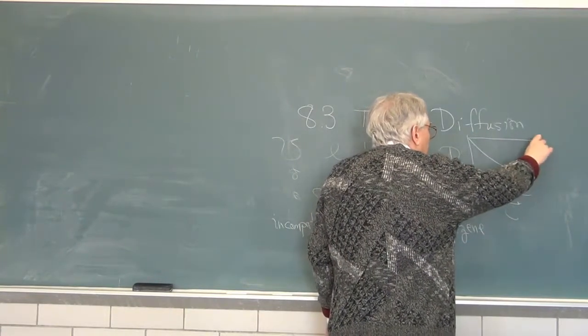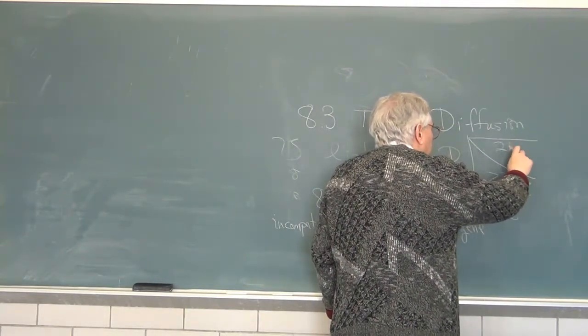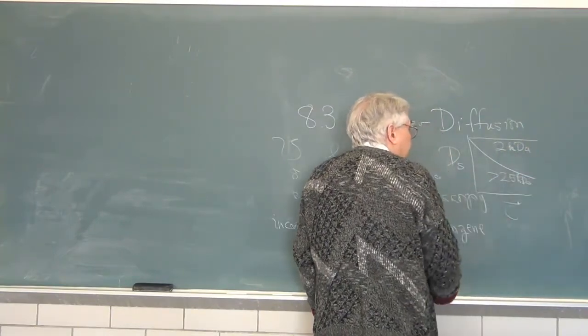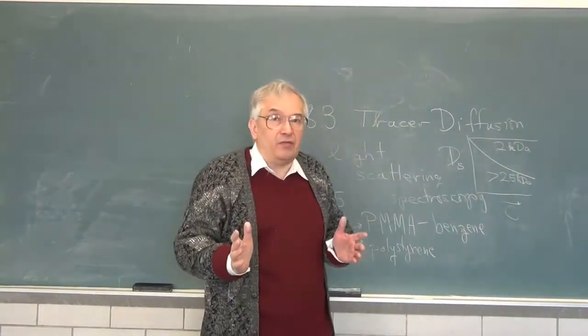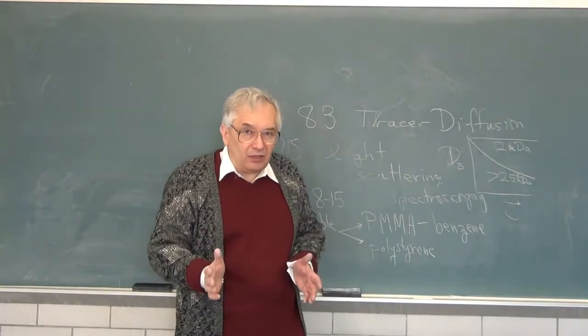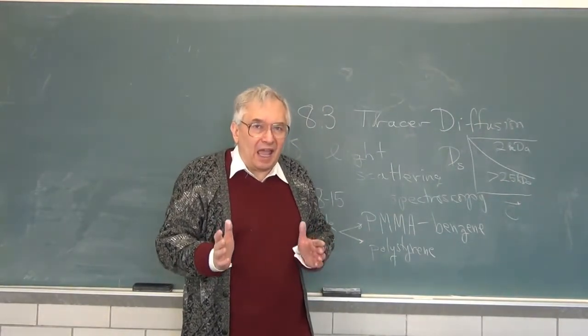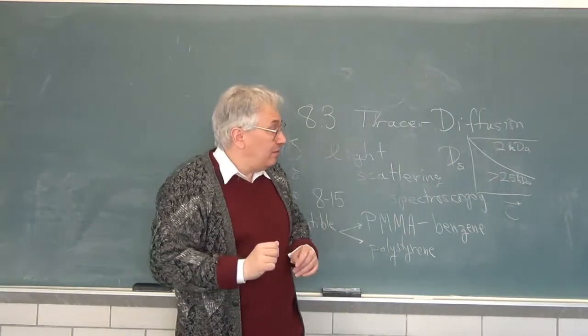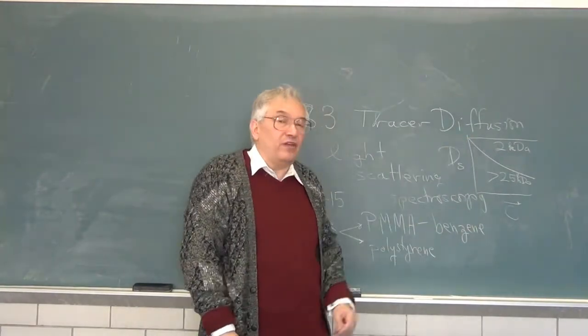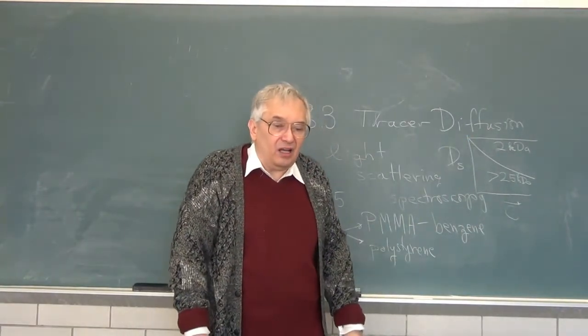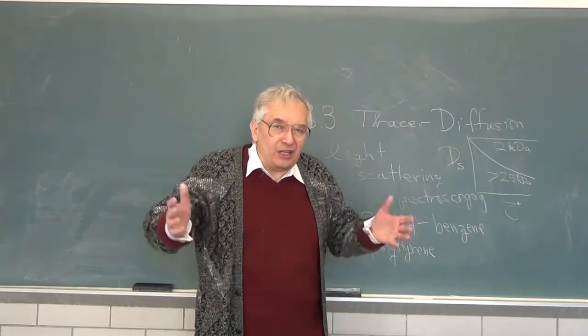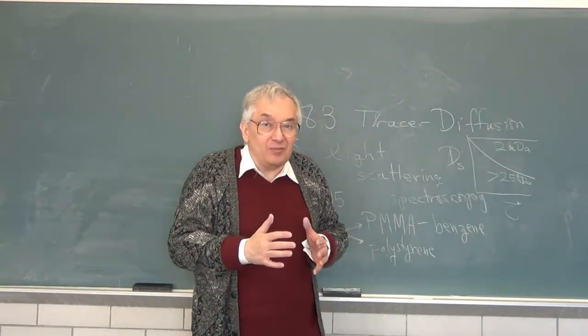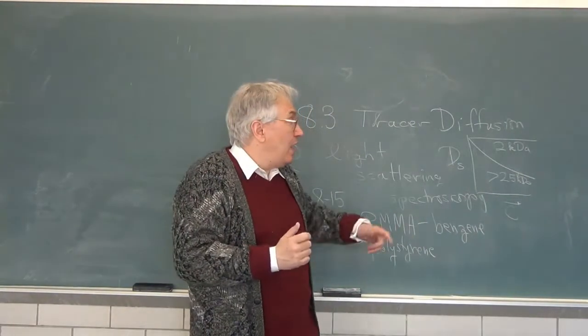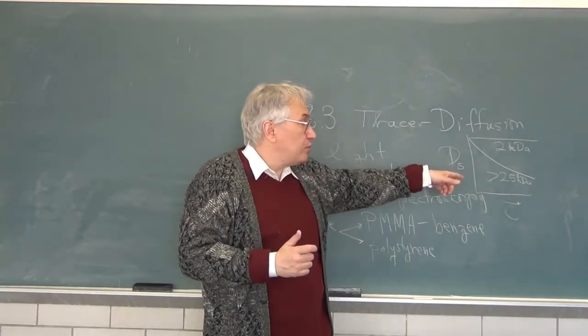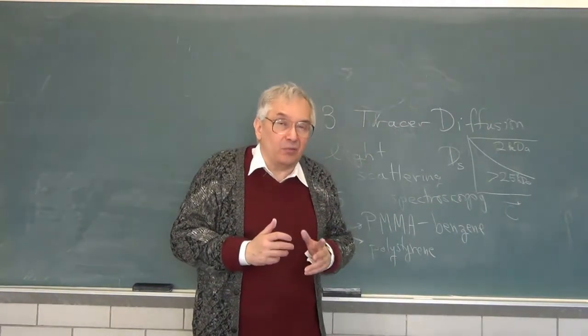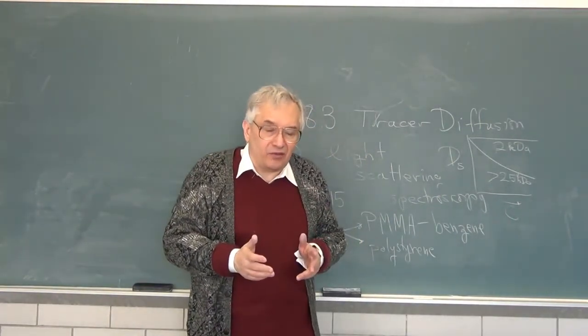But if we're down at a polymer of about 2 kilodaltons, which is a very low molecular weight, what happens is that the diffusion coefficient just sits there. The polystyrene chains don't shrink up on themselves because it's a very short chain. And also, they apparently aren't retarded very effectively in their motions by the presence of the matrix.